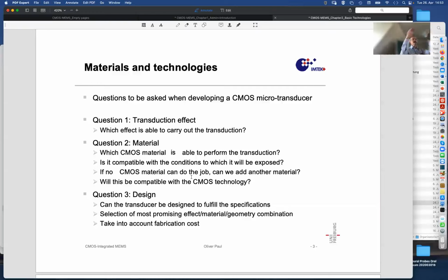So adding materials can be efficient, or removing materials can also be efficient to expose some properties that were not there before. Thermal insulation, for instance, in a thermal sensor: how do you achieve that? Silicon is a very good thermal conductor. If you would like to heat up a spot on the chip with some incoming radiation, or with the chemical reaction energy of some volatile organic compound with some added material on the surface of the chip, and you would like to measure a temperature increase, if there is a silicon substrate that immediately removes that heat, there will be no temperature change.